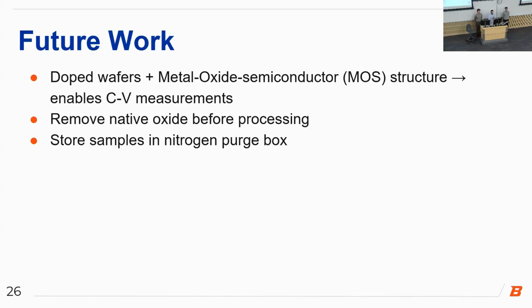For future work, there are three things we would consider doing differently. First, we would use doped wafers with a MOS structure, and MOS stands for metal oxide semiconductor, which would allow us to do CV measurements and directly measure trap density. Second, we would remove the native oxide from the samples before processing. So we start with a cleaner and more controlled surface. And finally, we would store the samples in a nitrogen purge box between steps to prevent them from reacting with air and affecting our result.